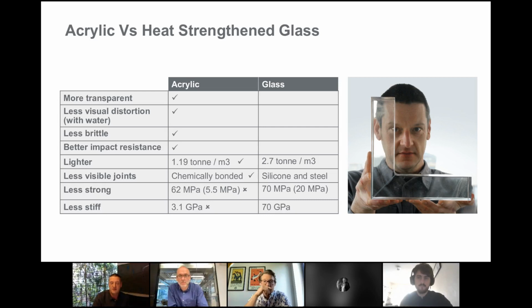It has better impact resistance. It's also less than half the density, so the structure's lighter. The joints are much less visible. They're chemically bonded rather than using silicone and steel. So, if you imagine a glass structure with all the silicone joints you'd have needed between those panels, the watertightness would have been a real issue.